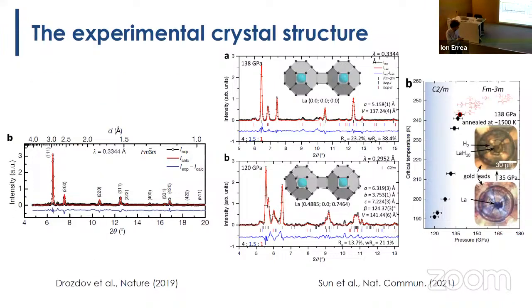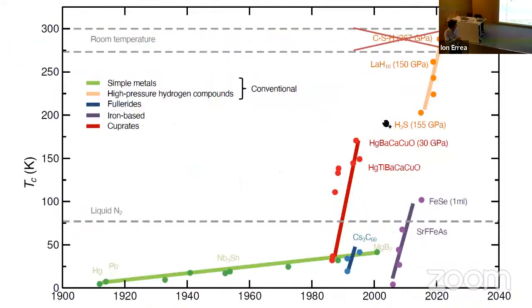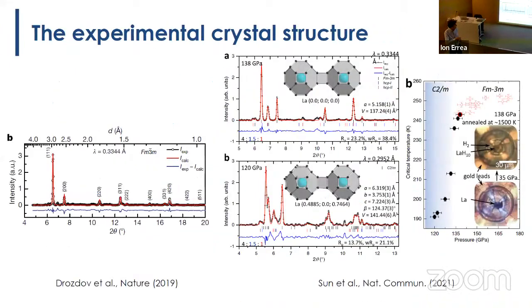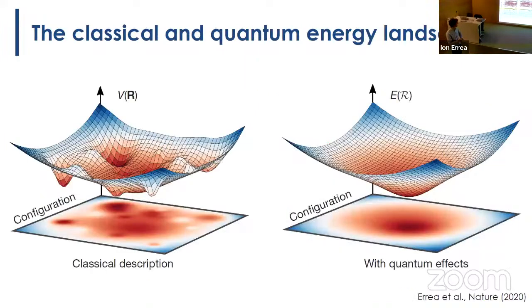Actually, you can see here in the experiment, when you go to the lower symmetry phase, the Tc rapidly goes down. So somehow, in all this pressure range, 100 GPa and above, this high Tc is kept thanks to quantum anharmonic effects. I believe this is the conclusion of this part.